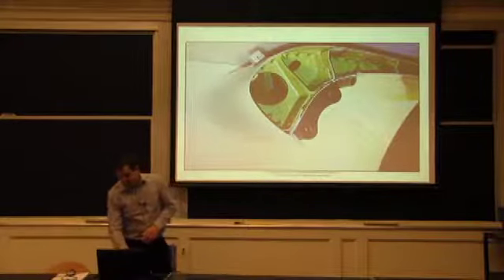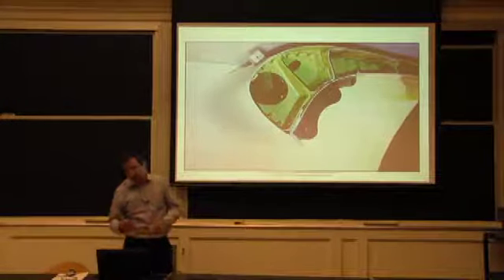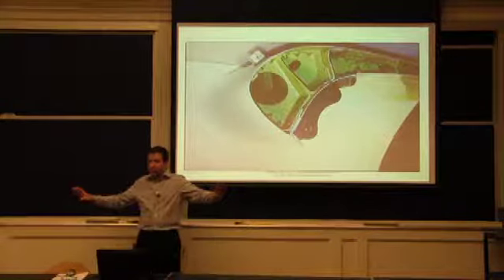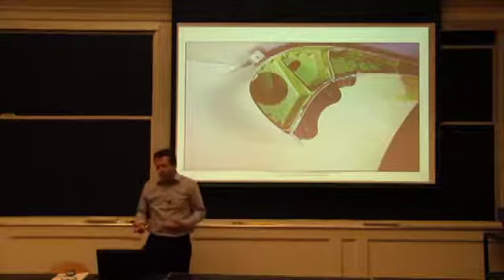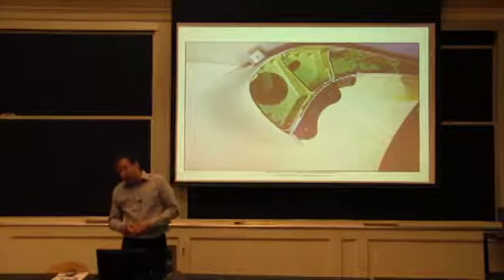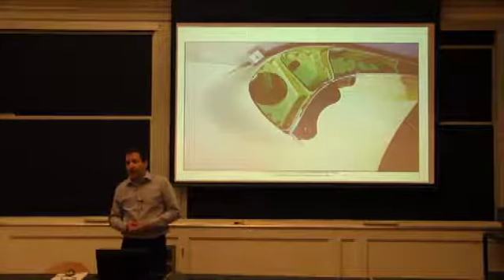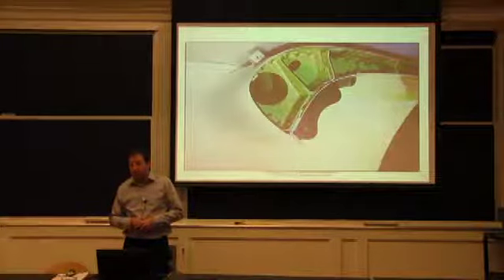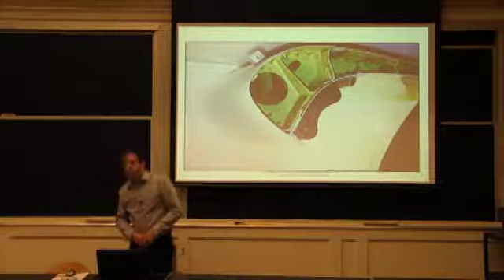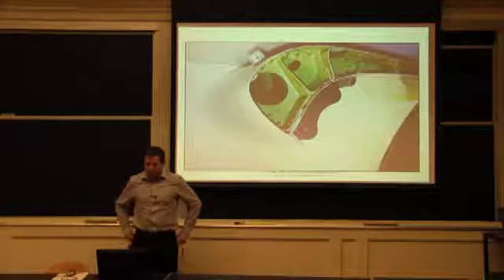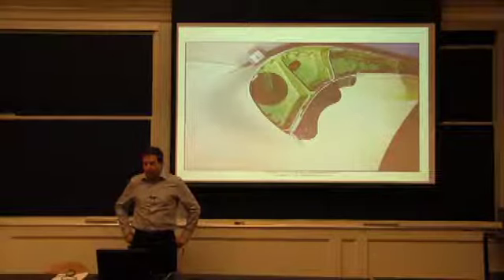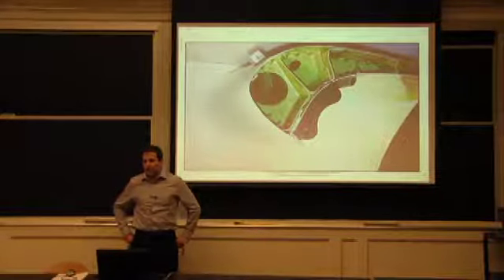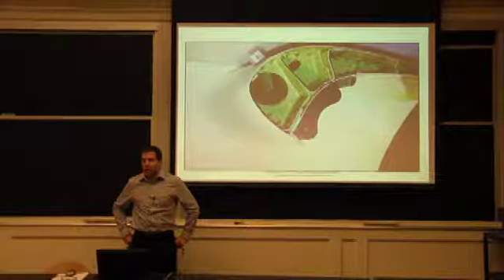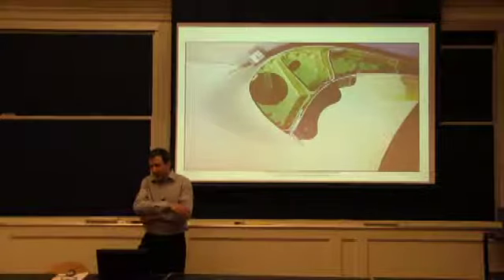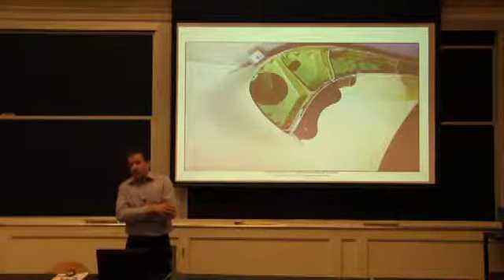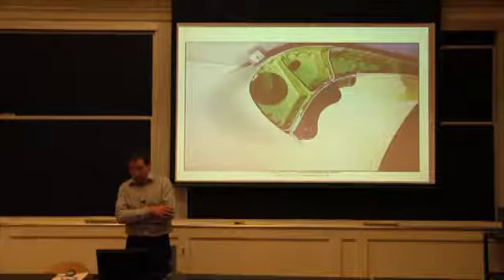When it's on the interior, here we have the benefit of looking at a cut piece. This was a test piece. But in reality, this wing is long, and you don't see all the ribs. So you don't see all the green pieces. So when we're talking about an acceptance criteria for a crack length, it would have to be a very long crack. It would probably have to be a fail-safe way of designing if you were to say, I'm going to allow this component to crack. So the way it was working out was essentially this should not be cracked, or if it's cracked, it should not grow to a significant length within the surface life of that wing component, which is always limited by a number of factors, and then you have to take it apart and really inspect it, because it's not easy to inspect it on a day-to-day basis.